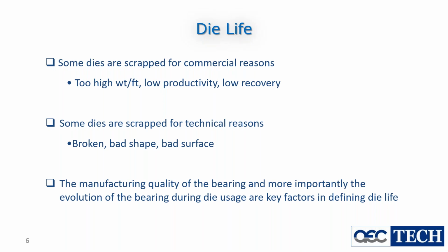There are 2 reasons that bring a die to the end of its life. I call them commercial reasons and technical reasons. A die can be too low a productivity to make it worth running. It can be too low a recovery for various reasons, be it front and back scrap or for bad surface, or it could be too high a weight per foot. If you're selling a section by the length, you really don't want that section to be heavy, because you're giving away all that aluminum. So a lot of extruders I know will retire a die because it's too heavy running.